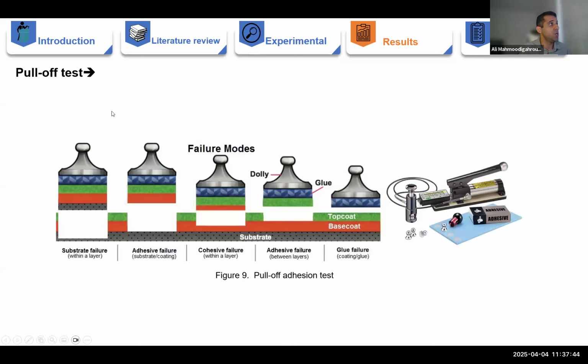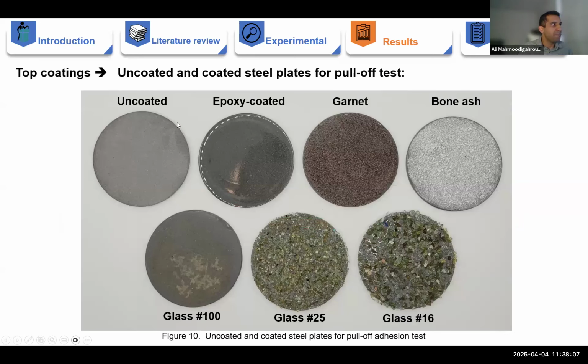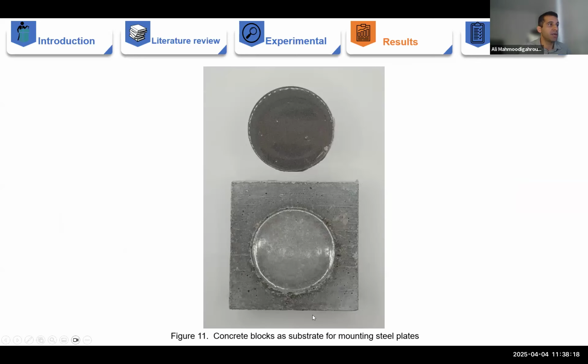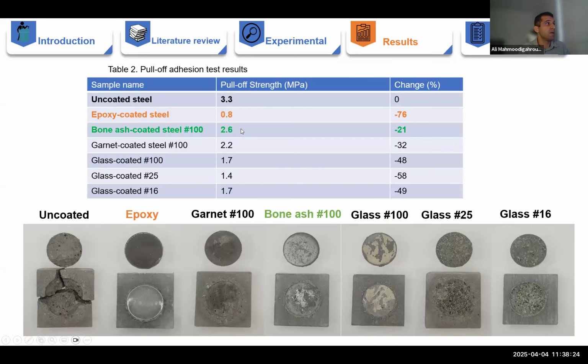For pull-off test, basically in this test, a fixture or dolly is attached to the surface of the coating and a vertical tensile load is applied until the coating detaches. And the force at which the detachment occurs is recorded as bond strength. We used these samples: steel plates, uncoated, epoxy coated, garnet, bone ash, and crushed glass with different particle size. And then the samples were mounted in fresh concrete. And after 28 days of curing, the samples were ready for pull-off test.